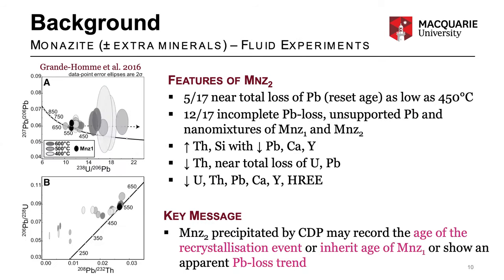5 of the 17 experiments that have been published were able to reset the age of their monazite with temperatures as low as 450 degrees Celsius. Although in most of the experiments, the modified monazite showed incomplete lead loss patterns, along with incorporation of common lead, like is shown in the figure. These patterns were inferred to be caused by analysis of monazite with unsupported lead or with nanomixtures of the precursor monazite and the new monazite. My key message looking at these experiments is that the monazite that's precipitated during coupled dissolution precipitation can record the age of the recrystallization event, or it can record these partially modified inherited ages of the precursor monazite, showing these apparent lead loss trends on a Concordia diagram.